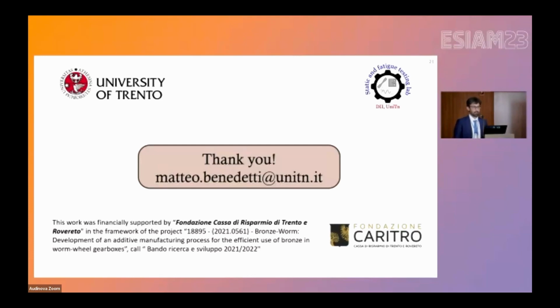Did you maybe try to use brass or bronze plating? For example, use a bronze as the anode and the gear as cathode and apply a current to get the thin layer of brass or bronze on the gear teeth? You mean a galvanic deposition? Yes, yes. Yes, we tried, but the delamination was an issue. So it's difficult to get a proper adhesion to the substrate in this case. Okay, thank you. Thank you.